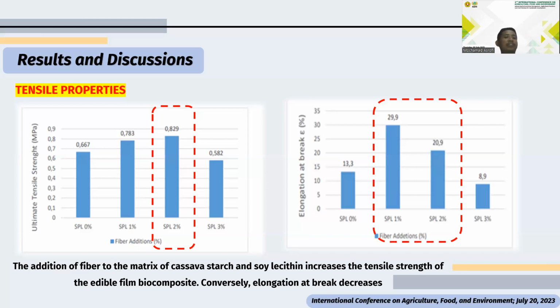From this picture, we know the addition of sugarcane bagasse fiber in the matrix of cassava starch and soy lecithin improves or increases the tensile strength. I mean ultimate tensile strength in here. The highest tensile strength was in the SPL 2%, the addition of fiber. This indicates there is a good interaction between matrix and fiber.